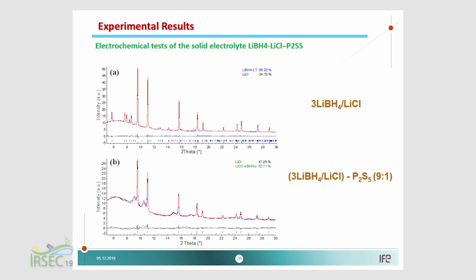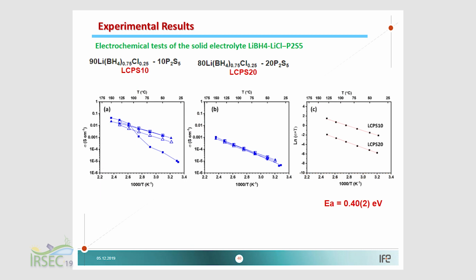when it's cooled down. So we could recognize here the lithium borohydride and the lithium chloride, and after addition of 10% of phosphorus sulfide, we could see a disappearance of lithium chloride, while we could still see the peaks of lithium borohydride. This was also studied by measuring the conductivity of two systems at different ratios, with 10% of phosphorus sulfide and 20% of phosphorus sulfide.